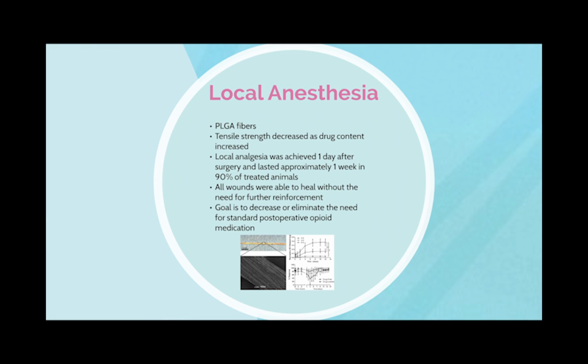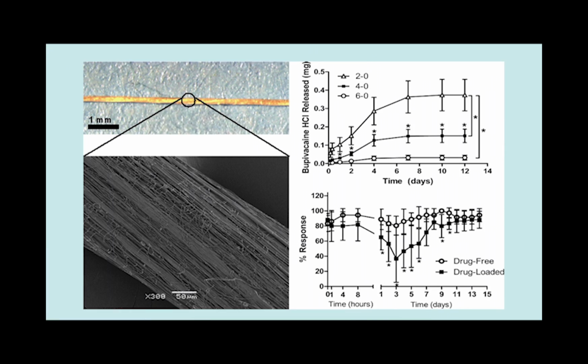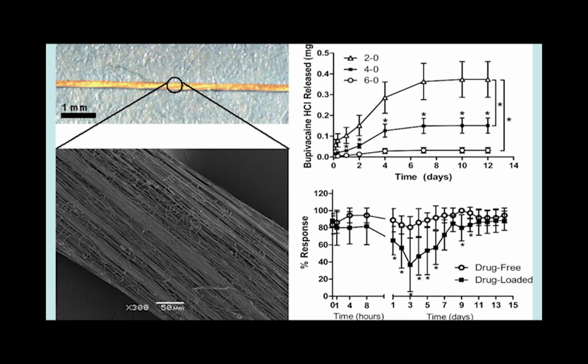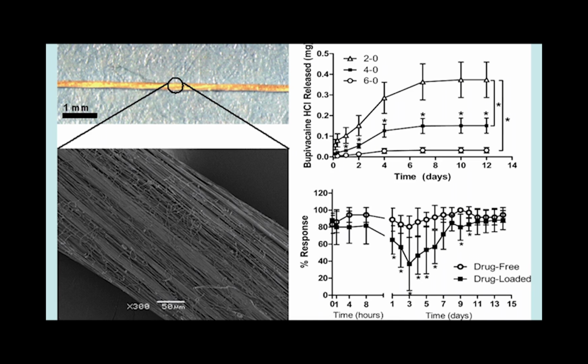The next one for local anesthesia used a PLGA fiber. They found that the tensile strength decreased as their drug content increased, and that local anesthesia was achieved 1 day after surgery and lasted approximately a week in 90% of their treated animals. All wounds were able to heal without the need for further reinforcement, so they were able to obtain that tensile strength, and they found that their goal is to decrease or eliminate the need for that post-operative opioid medication. And you can see in this image that their suture is actually not twisted like ours is. It's a little bit more straight, and there's not as big of a twist per inch ratio.